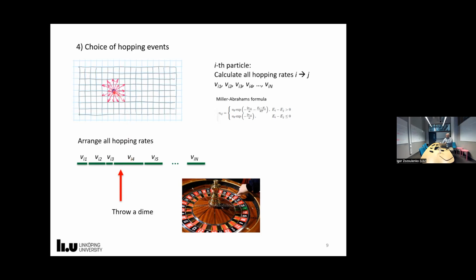Okay, so let us consider one particle. For this particular particle, using the Miller-Abrahams formula, we calculate all hopping rates from this site to all other sites. And then we arrange all hopping rates, and we simply throw a dice, so to speak, randomly, and therefore it's called Monte-Carlo. This dice will choose the hopping event according to this random distribution. But of course, the larger the hopping rate, the larger the probability that it will be selected.